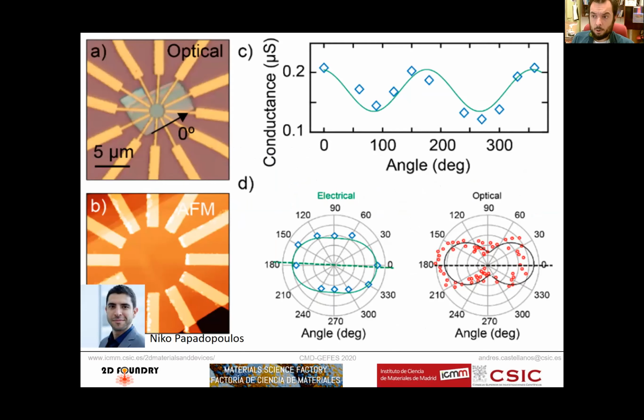We have also done electrical transport measurements on these kinds of samples, and what we have done is make electrodes at different angles in order to test the conductivity along different crystalline directions of the system. And we see again that the conductance of the sample depends on the direction. So we probe at different directions, and we see this sine wave here. Well, it's actually a cosine squared wave. And in a polar plot, you can see that it has this elongated shape. So there is indeed a clear in-plane anisotropy. And actually this anisotropy again matches the anisotropy that we see for the same flake in the differential reflectance, and therefore matches the position of these ripples.